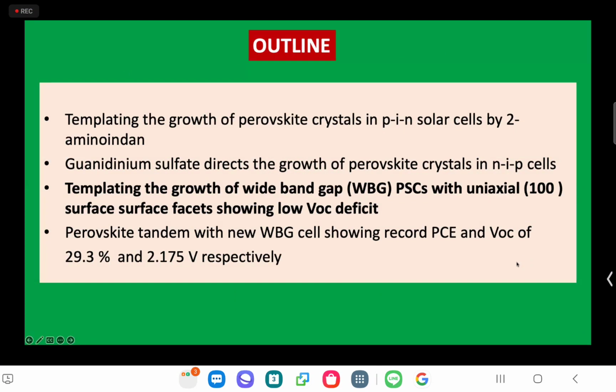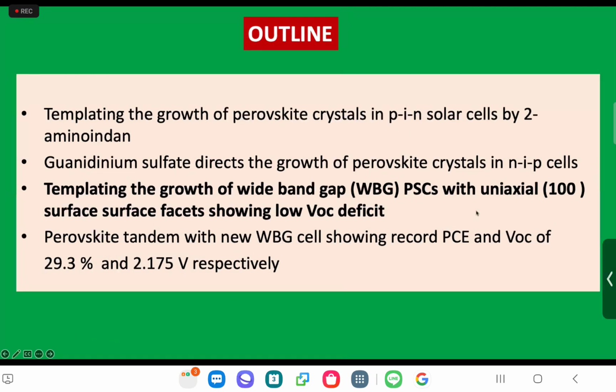Okay, good. So then now comes something very serious. We want to make a uniaxial growth. And how was that possible? Well, there's also an additive engineering. And this time, please listen very carefully, we added the phenylethylammonium, which is a very well-known 2D forming agent, to this anti-solvent, not to the starting solution but to the anti-solvent. This is different from the aminoindane, which was added to the initial starting solution, okay?